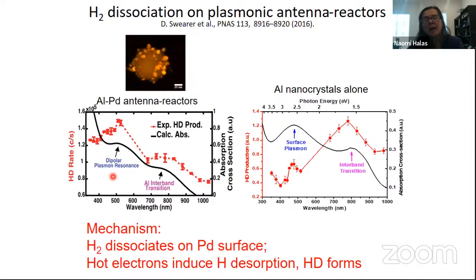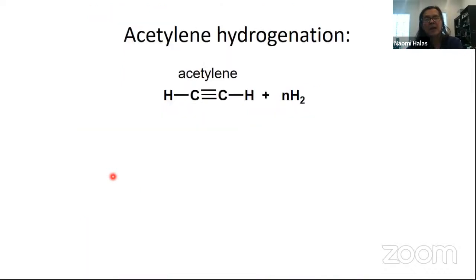So it turns out that as we excite the plasmon in the aluminum, the hot electrons can induce the desorption of the hydrogen atoms and kick them off. So we have now a stimulated desorption process of the hydrogen. Hydrogen is dissociated on the palladium, but the electrons within the palladium, which are driven by the electrons in the aluminum, so they're coupled to each other, will induce desorption, and we form HD on the surface. So this is the first example of an antenna reactor that we began to study.